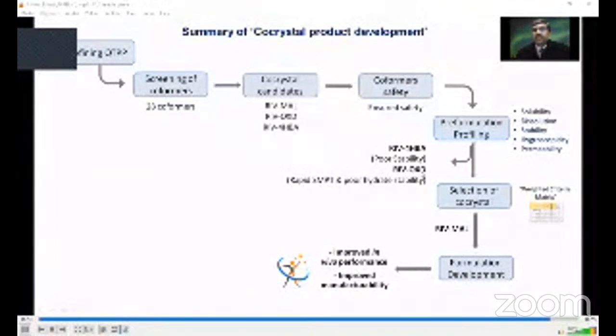The co-crystal with the oxalic acid had a rapid transformation to the pure API, which means the solubility advantage was not maintained for biopharmaceutically relevant time frame. It also showed poor stability because we saw certain degradation occurring in these cases. Based on this, the co-crystal was selected as rivaroxaban malonic acid using a weighted criteria matrix. We then developed the formulation using the optimal co-crystal candidate and obtained improved in vivo performance and improved manufacturability.